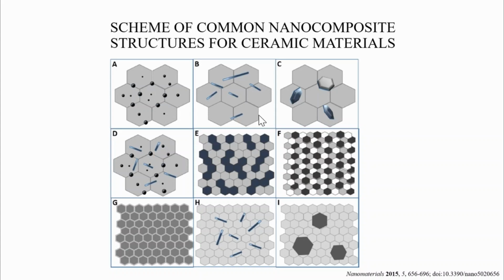Figures B and C depict other micro-nanostructures featuring elongated grains like whiskers, fibers, or rod-like grains, and picture C with nanoplatelets, all embedded within the micronic matrix. These structures are of interest due to the in situ toughening effect from the elongated grains and platelets, which contribute to crack bridging and deflection mechanisms.